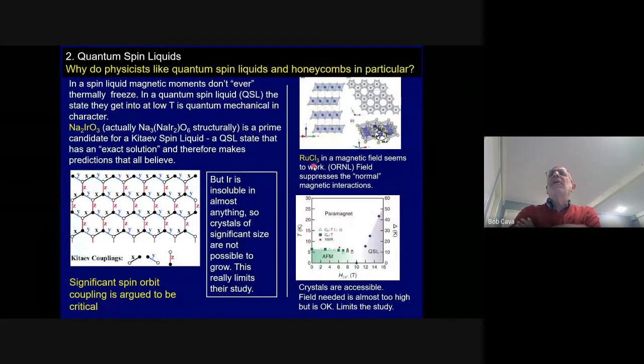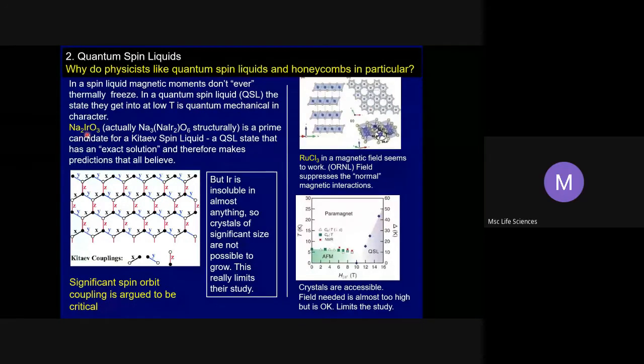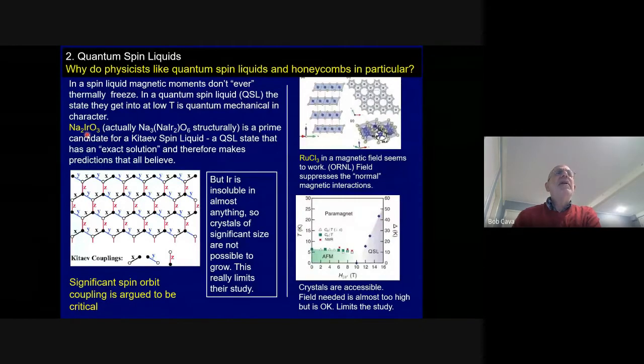Alternately, ruthenium trichloride has a honeycomb lattice. This was, I thought, a brilliant observation by these people at Oak Ridge, that you can grow crystals of ruthenium trichloride, which has a honeycomb lattice of ruthenium with nothing in a hole, and the ruthenium is bonded to chlorine. Now, the wonderful part about this is that it's chlorine, not oxygen, and it's ruthenium, which is a 4d element, not a 5d element. So iridium is a 5d element. Sorry, 5d element would be something from the bottom of the periodic table, where the unpaired electrons are in 5d orbitals. In ruthenium trichloride, the unpaired electrons are in 4d orbitals, so they're closer to the nucleus.